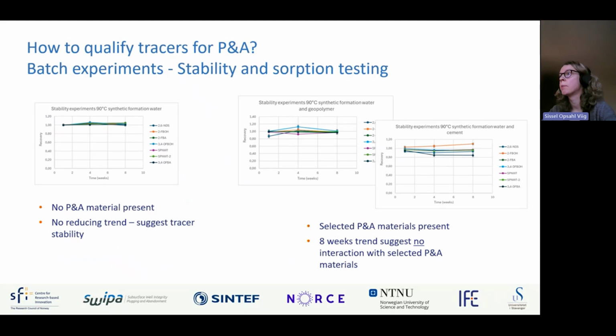This slide shows a brief overview of some of our results for the stability and sorption testing. On the left-hand side, you see results from temperature stability at 90 degrees Celsius, where the tracers are dissolved in synthetic formation water. On the x-axis, you see the exposure time from 1 week up to 8 weeks. And on the y-axis, you see the recovery. 1 is 100% recovery, meaning that the tracers are stable at the tested conditions. So here, no plugging material present. And as you can see, there's no reducing trend observed, suggesting that the tracers are stable for the time frame of the experiment.